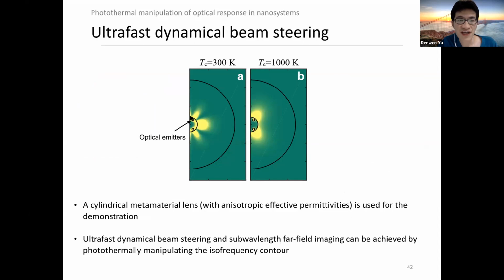So as an example, here we have two optical emitters sitting in front of this cylindrical metamaterial lens, bounded by these two semi-circles. And when the electron temperature of graphene is at room temperature, we can have multiple lobes in the far field. However, when we change the electron temperature, due to the modification of the isofrequency contour, we can modify the radiation pattern of these two emitters. And as a result, we can have this directional light emitting towards these two directions. And in the far field, we only have these two lobes.